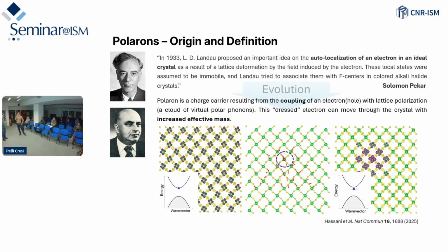In general, from my experience and the experience we had with Stefano, we characterize the small polarons with structural spectroscopies. If you see that the first environment is perturbed without propagating on a larger scale across the lattice, so just very localized. Yes, localized. So you did not take into account other neighboring sites? No, we have not performed any type of theoretical calculations. Obviously, we are open. I'm asking like a theoretician, because it's obvious that you use the term small polarons, so it's normal to ask.